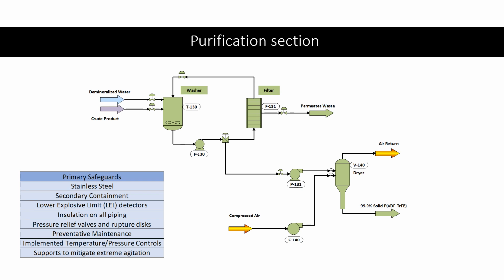The diafiltration process will take around 30 minutes. Once the product is purified, a 70% moisture content will replace the impurities, which will be evaporated using the fluidized bed dryer. This fluidized bed dryer uses compressed air pumped from below the trays through the fluid, leaving from the top. The operating temperature of the dryer will be around 100 degrees Celsius to evaporate the water, and once dried, the solid product will be transferred via conveyor belts to the solid product processing section, which I'll be talking about in the next slide.